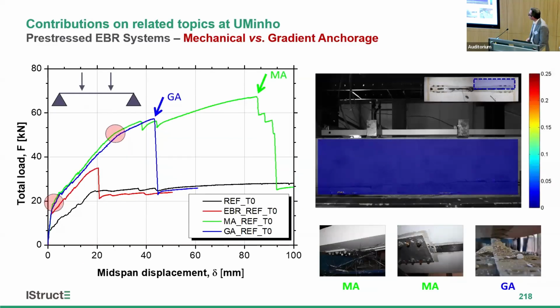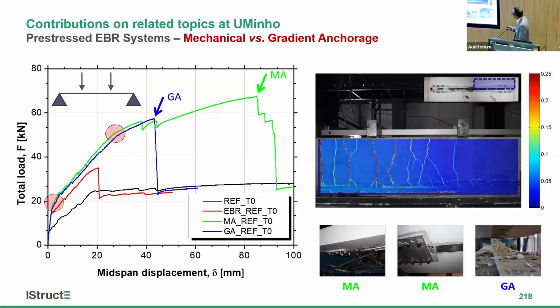Then we move also to some testing to compare the performance of both systems, and you can see here that both systems perform relatively well and similar until the failure by debonding of the gradient anchorage, because it doesn't have these anchorages. While in this one we can avoid this premature debonding due to this metallic anchorage. So this is the reason that we have a little bit higher capacity and of course much more ductility.